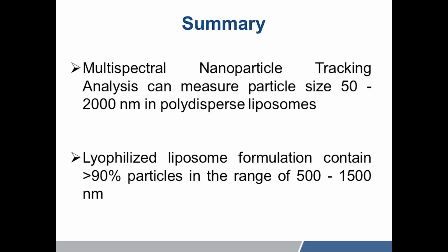So just to summarize this, multispectral nanoparticle tracking analysis can measure particle size very well between 50 to 2000 nanometer in polydisperse liposomes, and it works well with the lyophilized liposome formulation that we have, and we determined that more than 90% of particles are in the range of 500 to 1500 nanometer size range for the polydisperse liposomes LVAT that we have used. One thing I would like to mention here is that we have used only the nanoparticle tracking analysis application